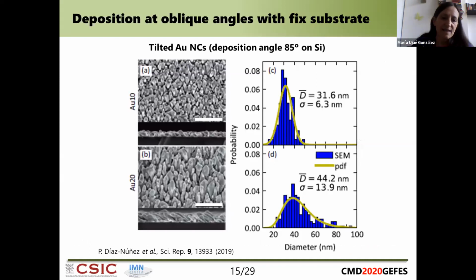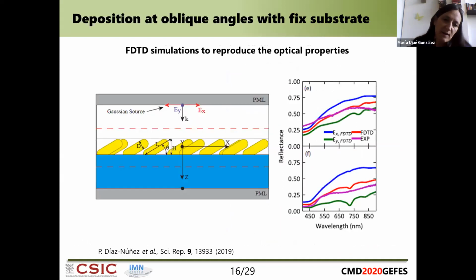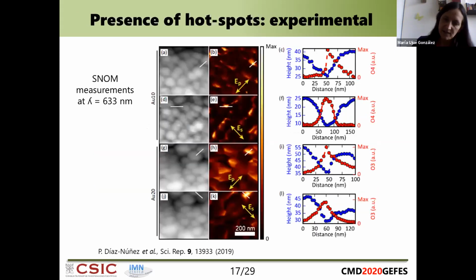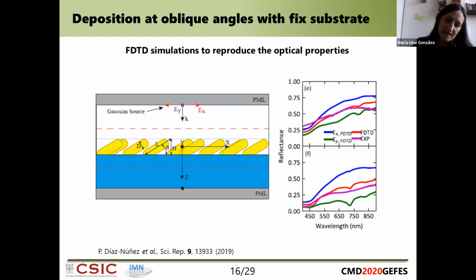Well, the first thing was to get an idea of the properties I already mentioned before, but we did the analysis from the images to have an idea of the diameters and the distribution, because this will allow us to have a FDTD model, a simple one, but to try to understand a little bit the optical properties of the system. So we simulated the nanocolumns as being these structures here, with the inclination, the length, and the diameter we obtained from the SEM characterization.